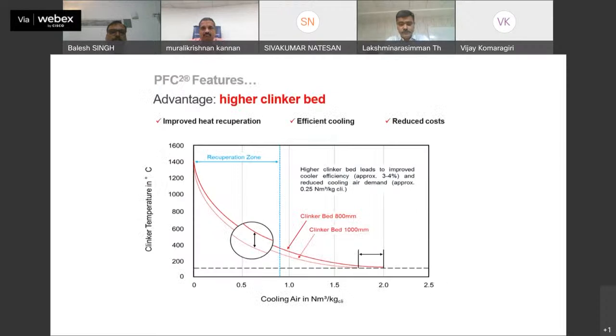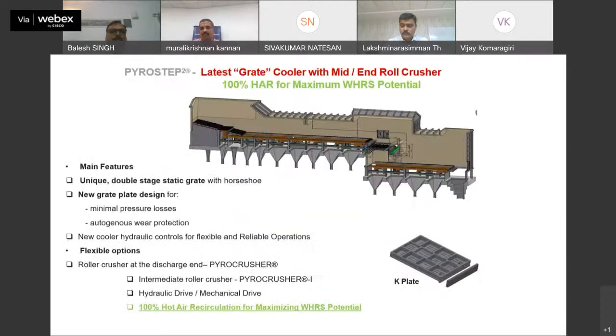So these are examples showing what effect comes if we are using a clinker bed of 800 mm and when we are using a clinker bed of 1000 mm. When we are using a 1000 mm clinker bed, our cooling air amount reduces to 1.65 to 1.7 Nm³ per kg clinker, and when we are using a clinker bed less than 800 mm, then it may require 1.8 to 2 Nm³ per kg of clinker.